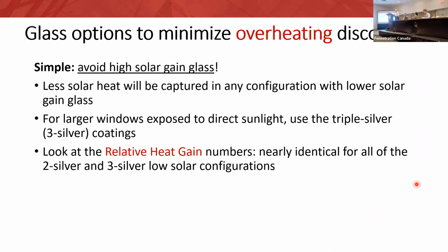So yes, if you're expecting a lot of solar heat gain, use the triple silver coating for sure. And then look at the relative heat gain numbers. They're nearly identical for all of the 2 and 3 silver low configurations, because the relative heat gain is triggered by how much solar heat gain you block, no matter how many layers of glass and coatings you have after that.